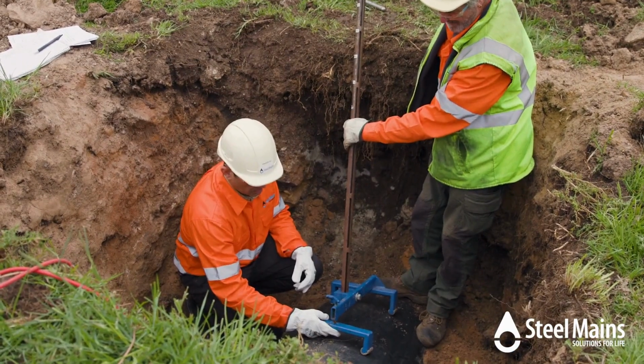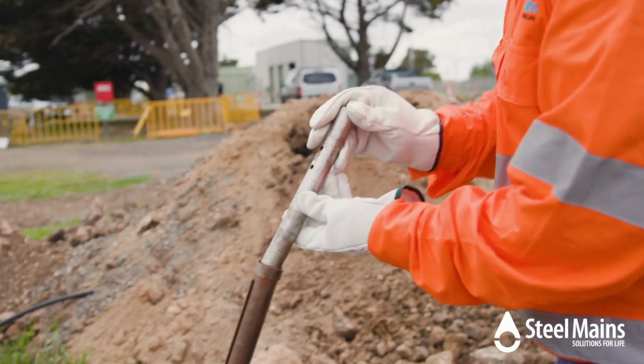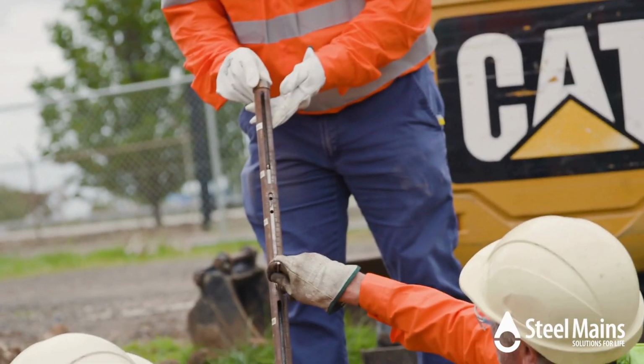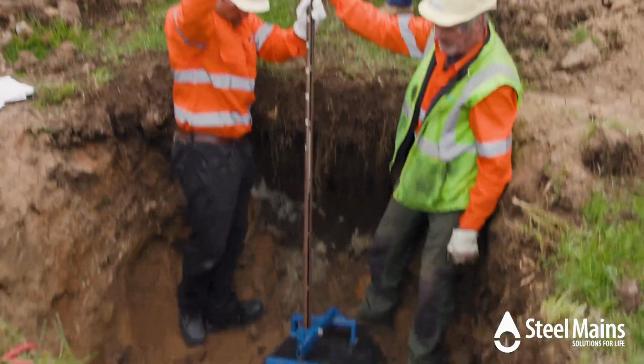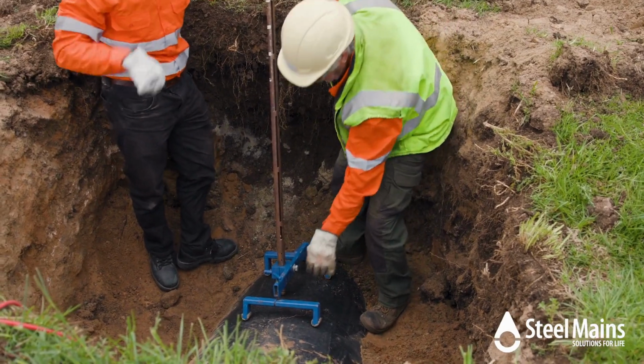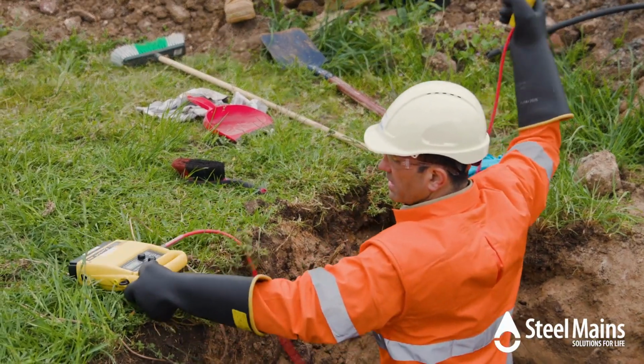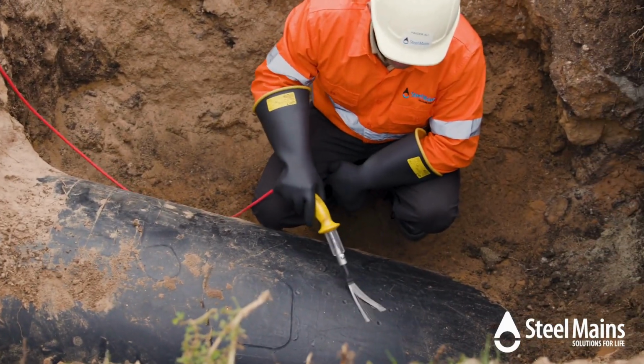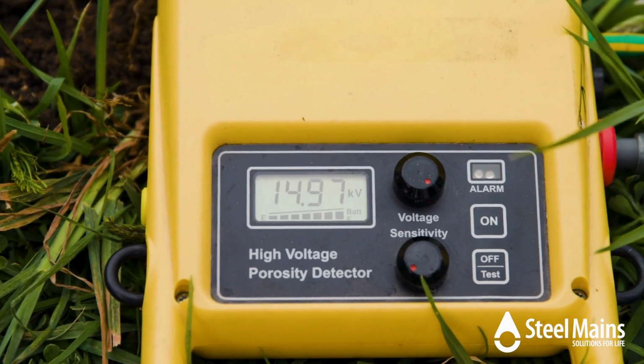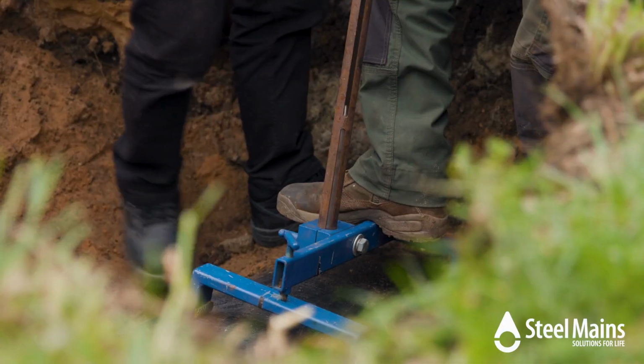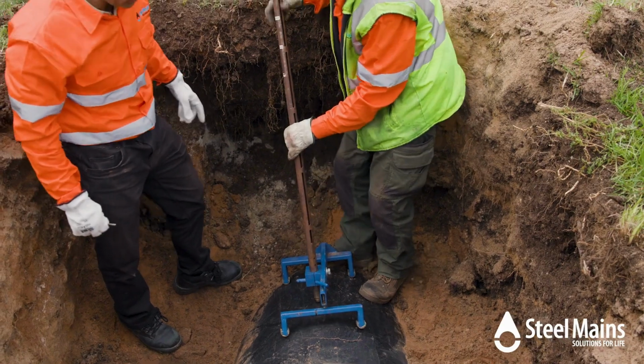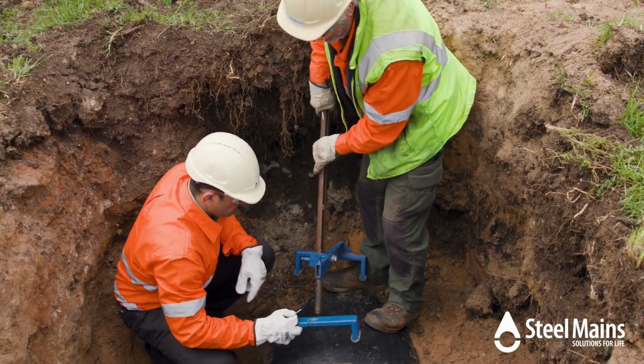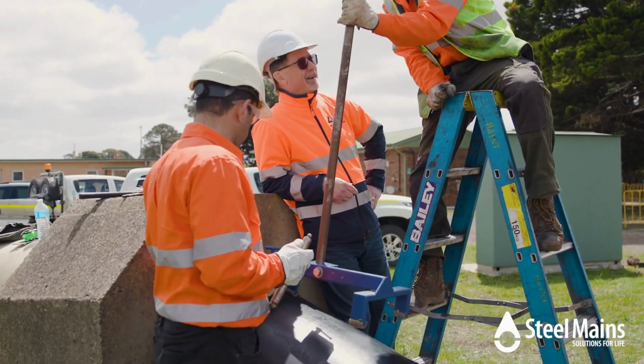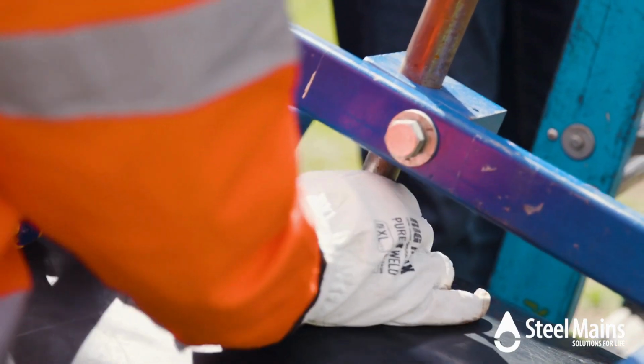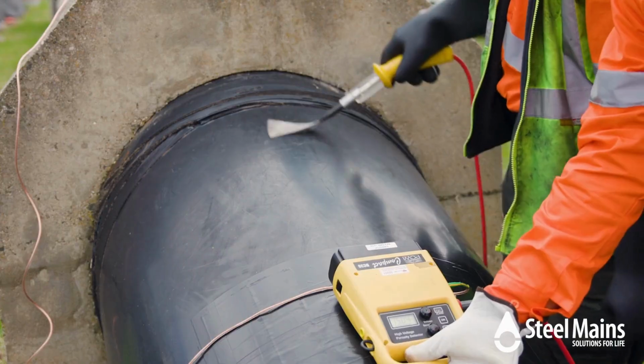Next, we conduct an impact test. This measures the coating's resistance against the same performance standards required for a new pipe. To pass, the coating must withstand 15 joules of impact energy without holidaying, that is, without exposing the steel beneath. At 15 joules, both sections of the pipe pass the impact test and remain holiday-free. This demonstrates that even after nearly half a century in service, Sintercoat continues to absorb impact loads without breakdown or failure, above and below ground.